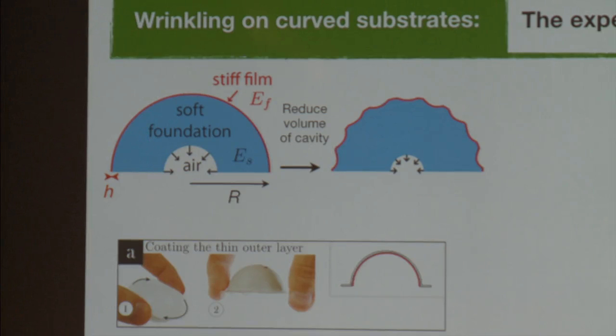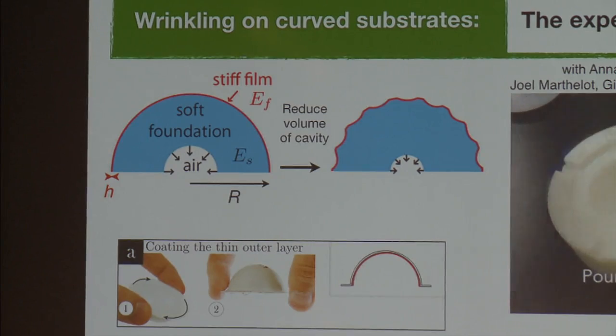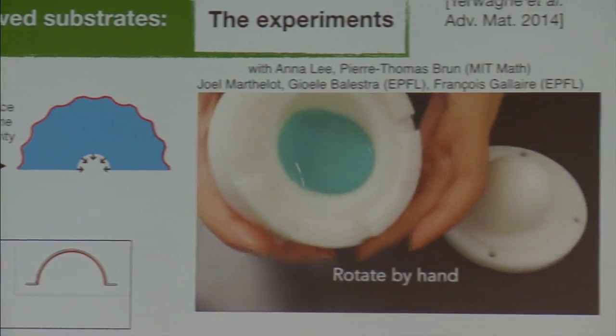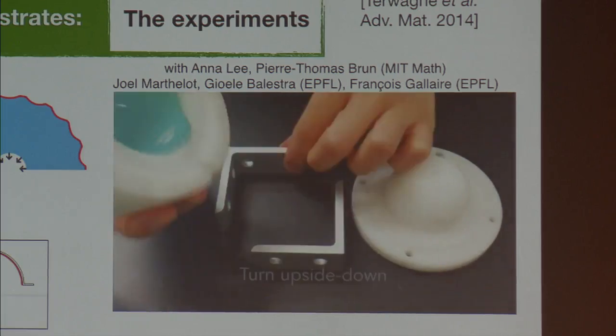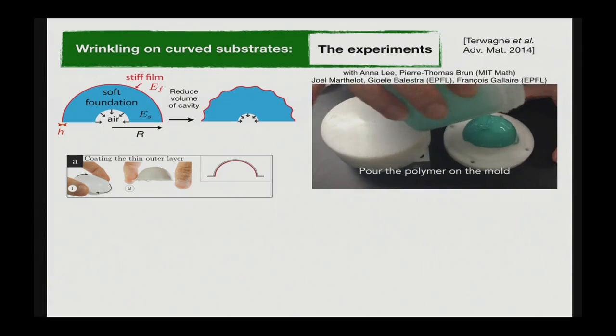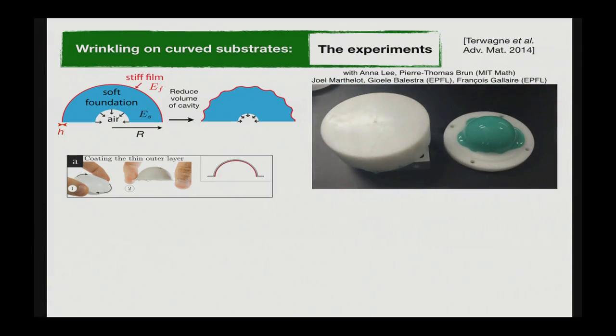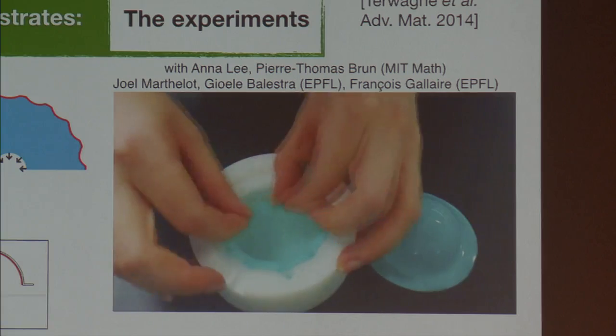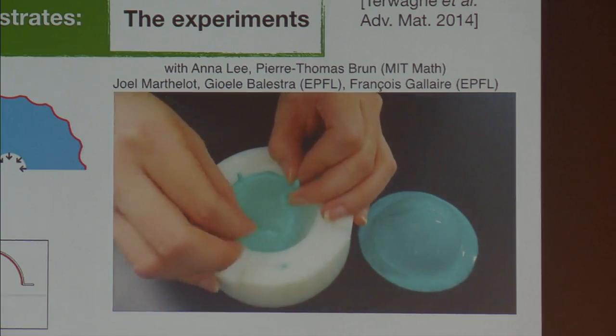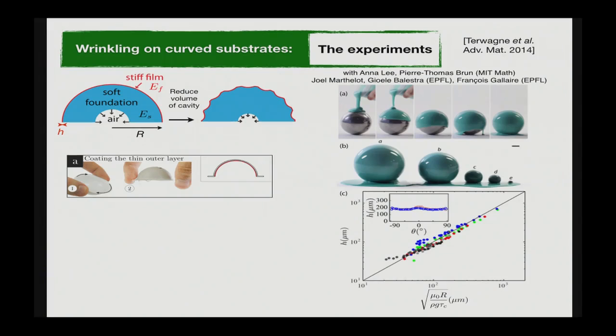And we're going to depressurize this cavity in order to apply compression. So it's actually, well, just a little aside. This has actually turned into a project of its own. How do we even make these thin shells, which are not graphene thickness, but you can also not make them by casting? We use a coating method where we pour these polymers over a curved surface. They're getting thinner because of drainage, but there's a magic balance between gravity, polymerization rate, and viscosity, such that the thickness that we get is constant within 5%. It's magic. You'd have thought that the top would be thinner than the bottom. That's not the case. And so we can actually design for shells of different thicknesses, and we know the parameters, how it depends on viscosity, on the radius, on the curing time, and so on.